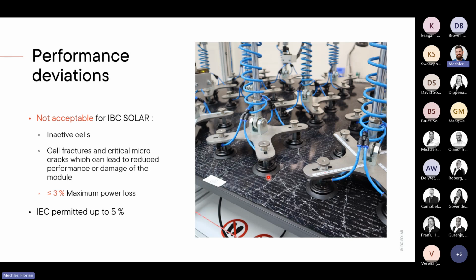Perhaps what is also very interesting for us: it's not acceptable to have any inactive cells, any micro cracks or anything else, and we say up to 3% power loss is the maximum allowed after the static load test. The reason we said a maximum of 3% is still okay is because of the instruments, which cannot measure better than 3%. IEC permits up to 5%. So we are quite near half of the IEC regulation. Our test conditions are much harder than IEC.